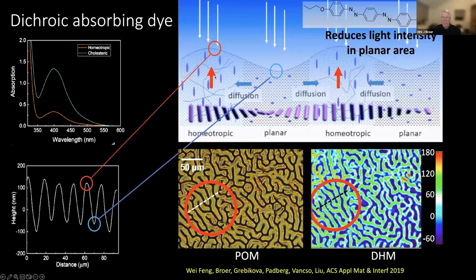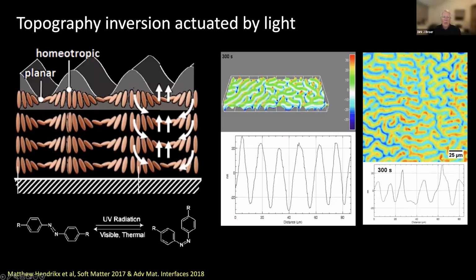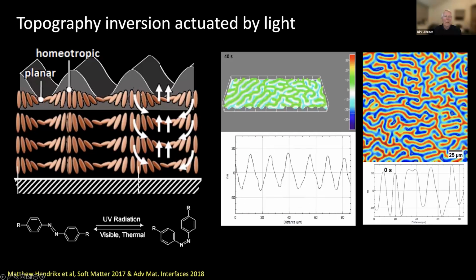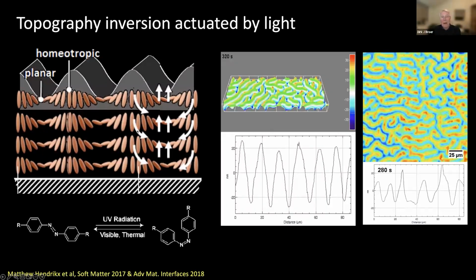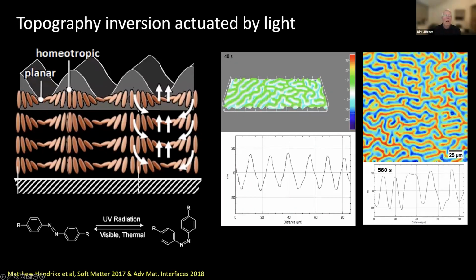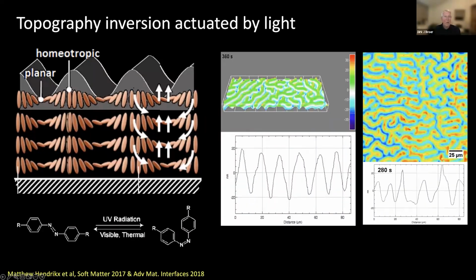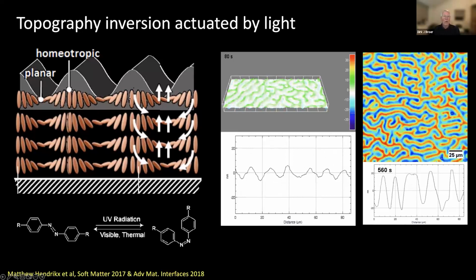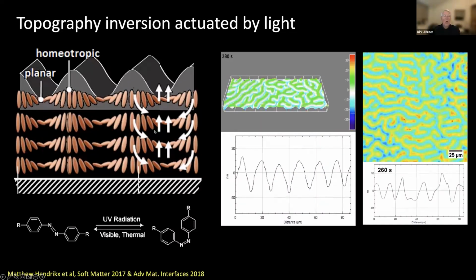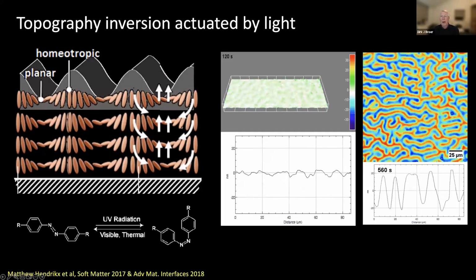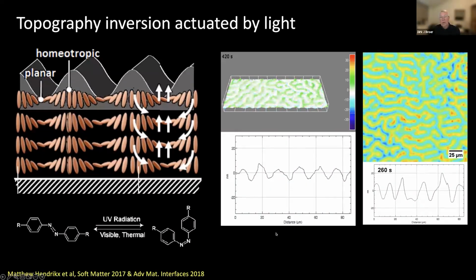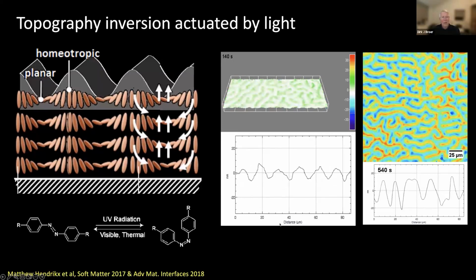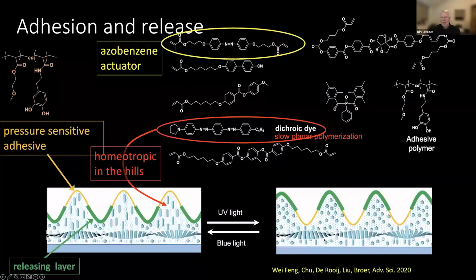So this is the case now. We create a corrugated structure, and this corrugated structure can now actually, by again using this actuation by light, we can invert it. So the higher perpendicular area is now shrinking, going down, and the planar area goes up. So what is initially high becomes low, and what is initially low becomes high, and this all on a time scale of seconds in this case. And this is interesting because you can actually use it for a special application for adhesion and release of a gripper in this case.